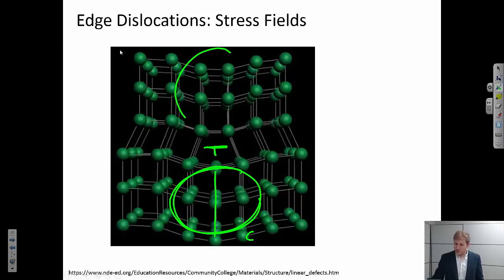Looking at the opposite view, the region on the opposite side tends to be in tension. T for tension. And I could think about that just the inverse case, right? Instead of adding an extra half a plane, let's say I subtract half a plane above. Now the atoms are relatively further apart than they would be in equilibrium, and so they're all under tension.